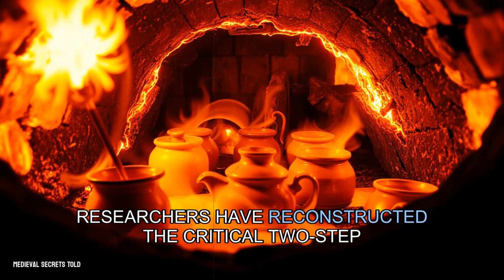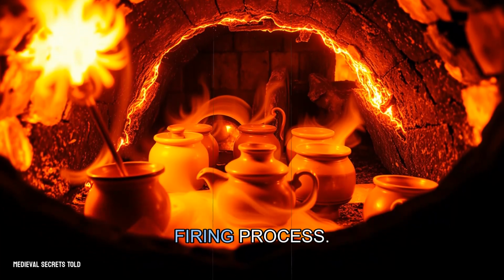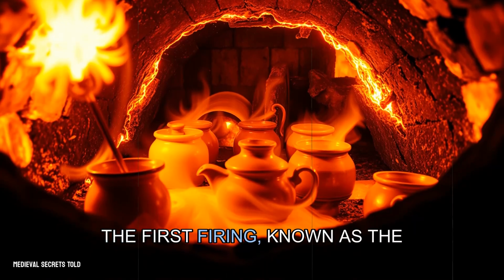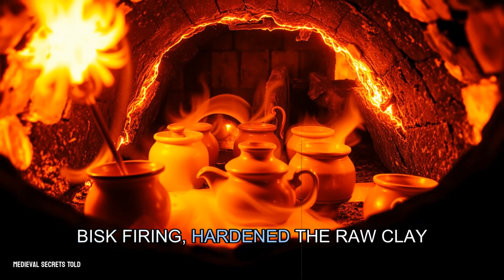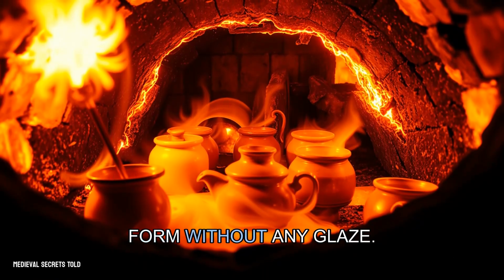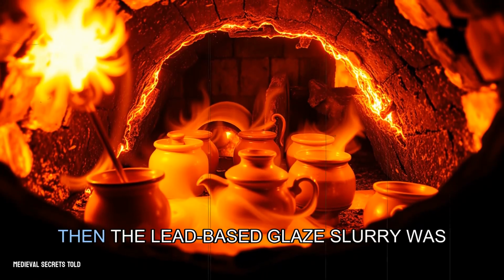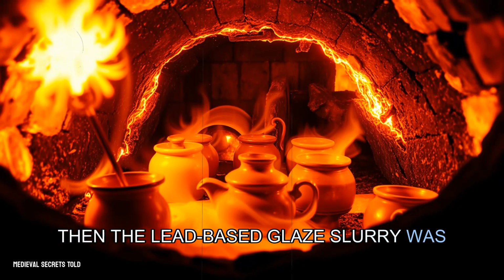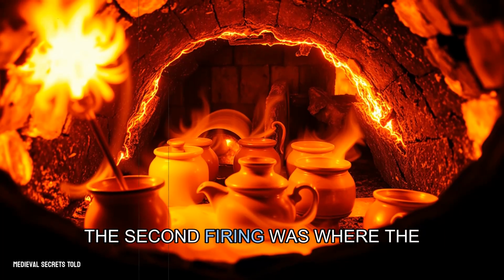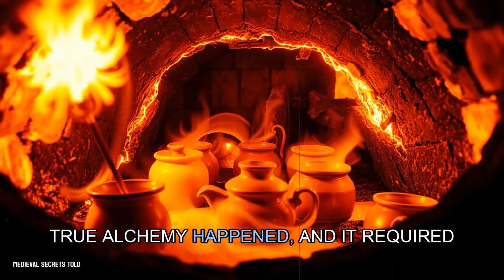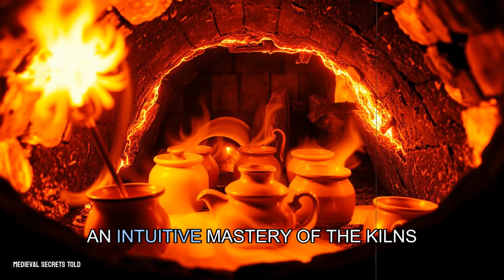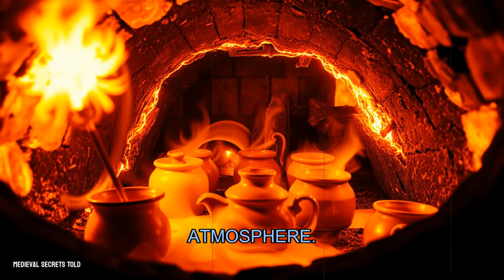Researchers have reconstructed the critical two-step firing process. The first firing, known as the bisque firing, hardened the raw clay form without any glaze. Then the lead-based glaze slurry was applied. The second firing was where the true alchemy happened, and it required an intuitive mastery of the kiln's atmosphere.